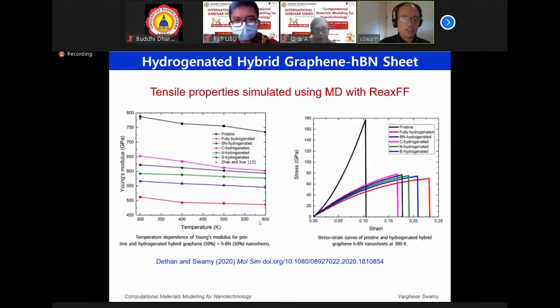So just to summarize the results obtained for various configurations of the hybrid structures, the Young's modulus as a function of temperature is shown here for various configurations of hydrogenation. So this is pristine, meaning no modification, graphene and HBN hybrid as it is. You can see that at low temperature, the Young's modulus is high, and with increasing temperature, it decreases almost linearly. On the other extreme is the fully hydrogenated structure. That means in this material, for every atom, we have an attached hydrogen species sitting there. You can see that there's a huge drop in the Young's modulus.